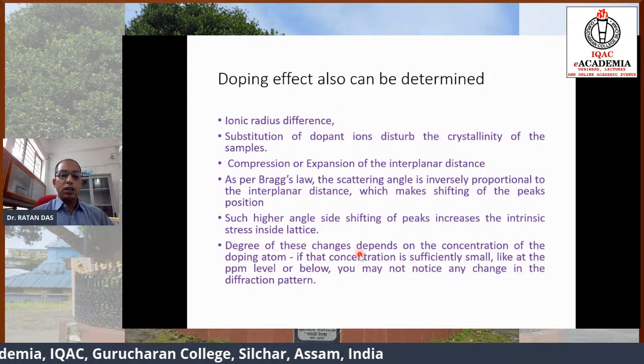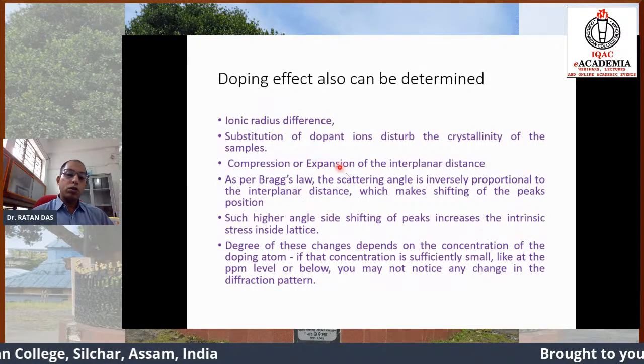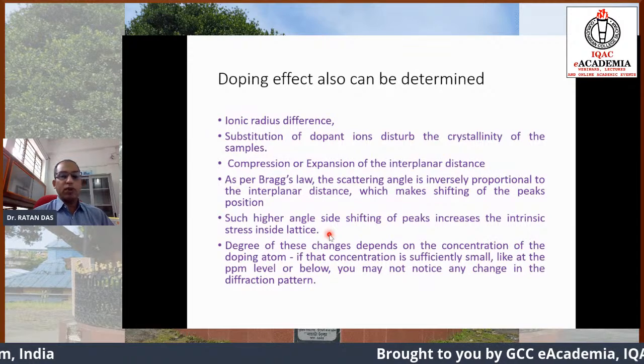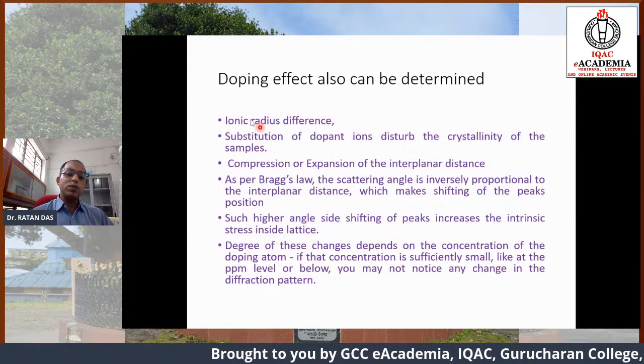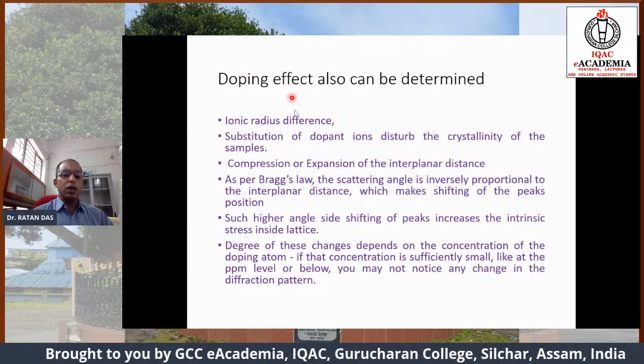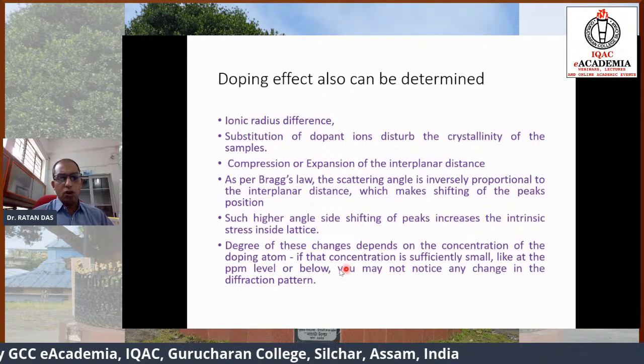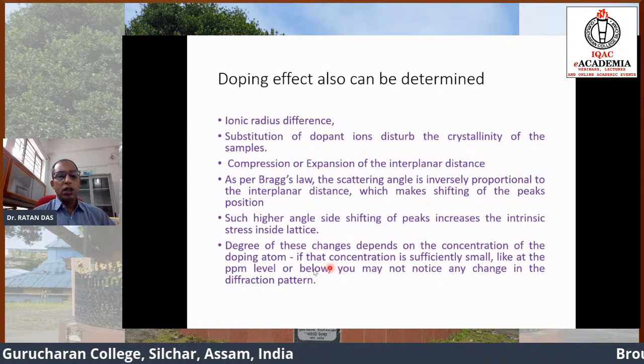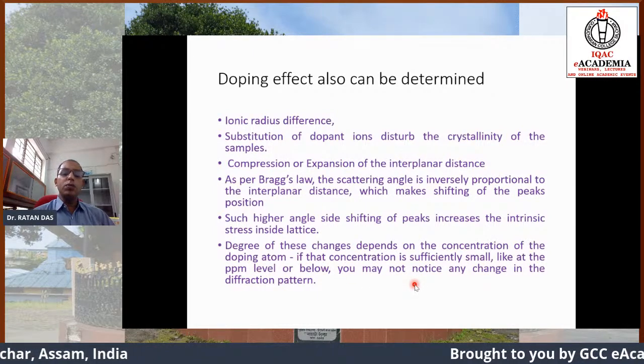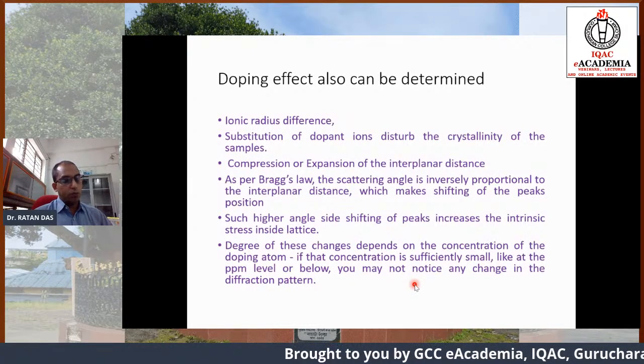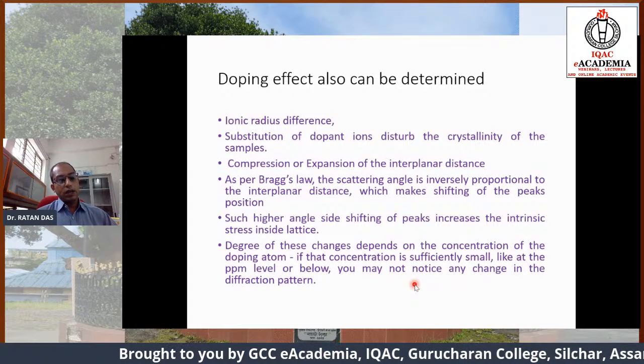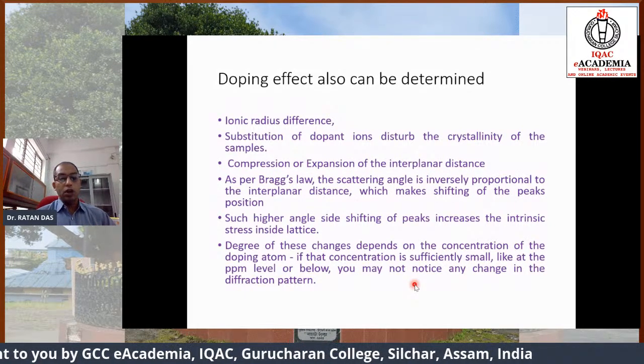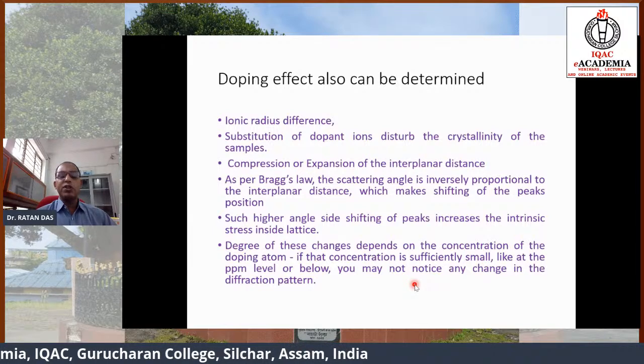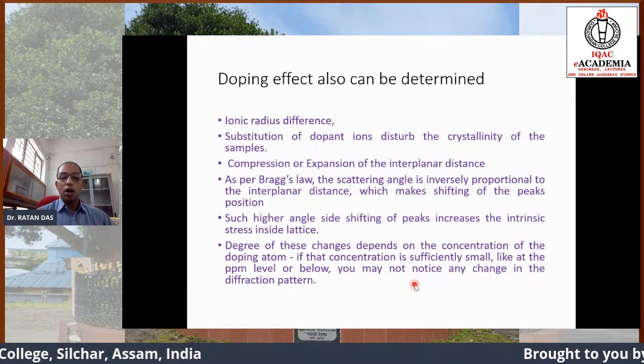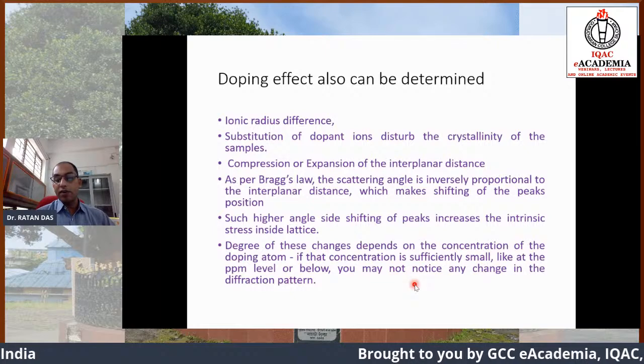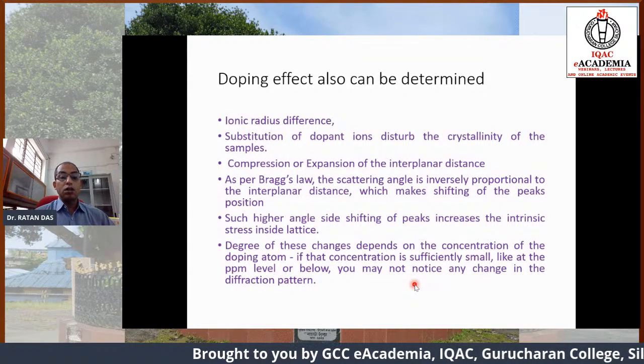So the degree of these changes depends on the concentration and on the size confinement. If the doping concentration is sufficiently low, then you may not notice any change in the diffraction pattern, because the shifting will not take place by a large amount. Shifting will take place by a very small amount compared to your reference material.